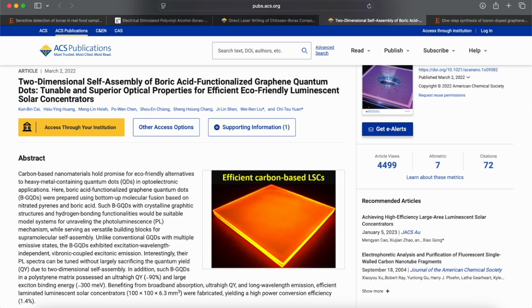Unlike conventional graphene quantum dots with multiple emissive states, the boric acid functionalized graphene quantum dots exhibited excitation wavelength independent, vibronic coupled excitonic emission. Interestingly, their PL spectra can be tuned without largely sacrificing the quantum yield due to two-dimensional self-assembly. In addition, such boric acid graphene quantum dots in a polystyrene matrix possess an ultra-high quantum yield and large exciton binding energy, benefiting from broadband absorption, ultra-high quantum yield, and long wavelength emission.